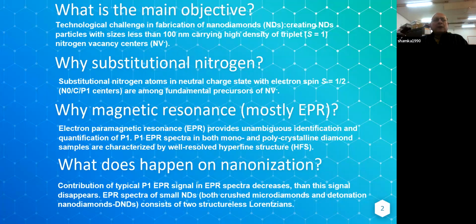And without having a certain amount of P1 centers, also called N0 or C centers, you cannot manufacture fluorescent diamonds. And this is a very, very important precursor. Why just magnetic resonance? There are a lot of other spectroscopic methods with which you can detect different nitrogen defects. But electron paramagnetic resonance provides unambiguous identification and quantification of P1. Very, very precise, very, very reliable.